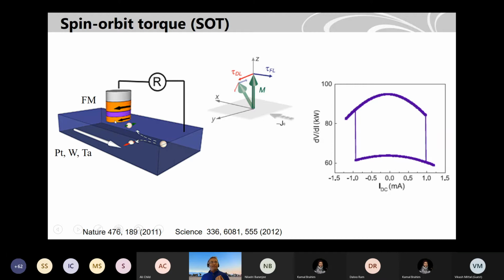Then you put a magnetic element here, a nanomagnet, with some magnetization orientation. It can be in plane or out of plane, so you have to deal with other basic things here to switch those magnets. But when you apply a current here, you create spin, with the red spin going down to the other surface and the green spin going up to the top surface, and this green spin can switch this magnet. Okay, and how to read that out? You can put a tunnel barrier and put another magnet. When the lower magnet close to this metal switches, you can see a change in the resistance depending on the magnetic orientation between both of them. So what you will see is switching in your resistance.